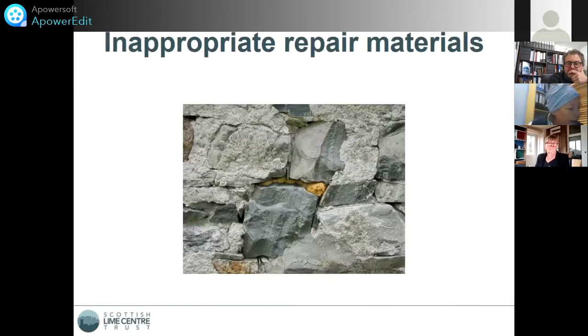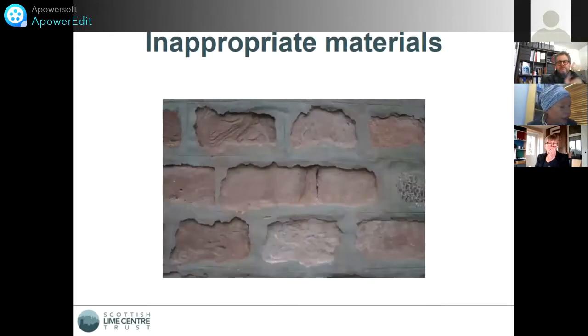So we can see here that somebody in their great wisdom has used expanding foam as a repointing, jointing material, totally not acceptable. And again, another example of inappropriate materials which are having a deleterious effect to the masonry units, in this case a pinky reddy sandstone, which as Katie pointed out, water will find the path of least resistance, and in this case the sandstone being weaker than the cement jointing material, accelerating its decay, leaving the cement joints and beds proud. This is what we want to avoid.